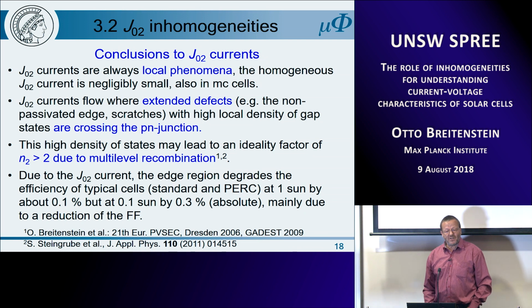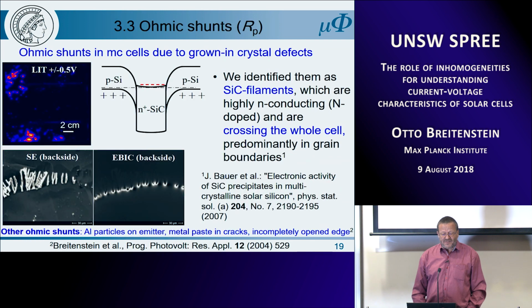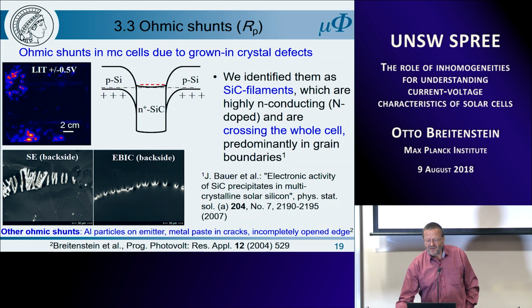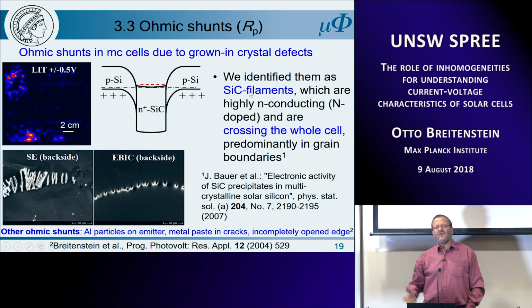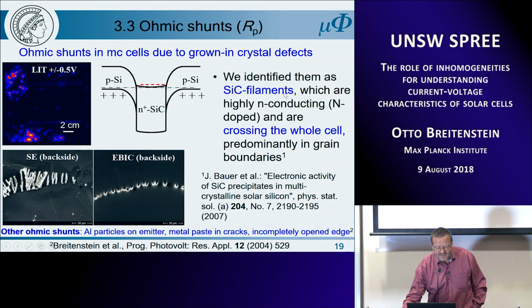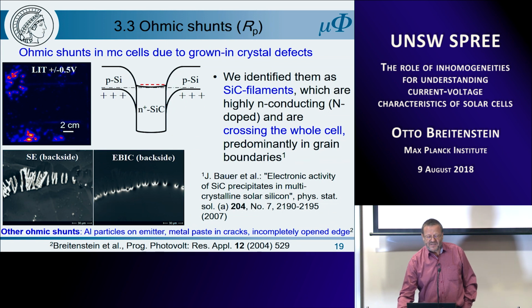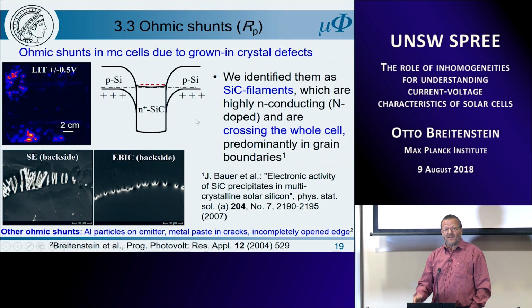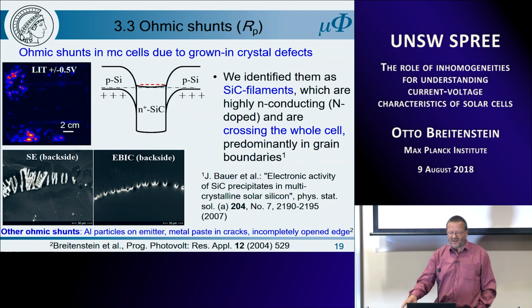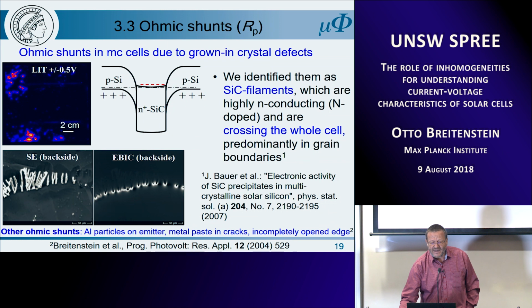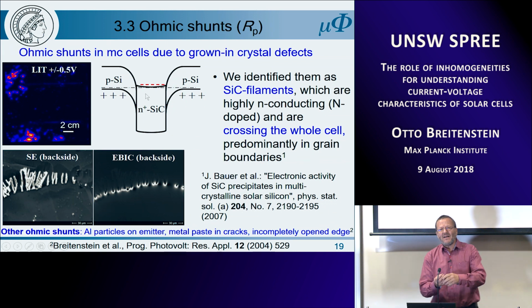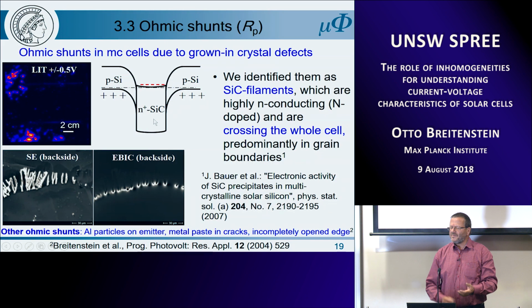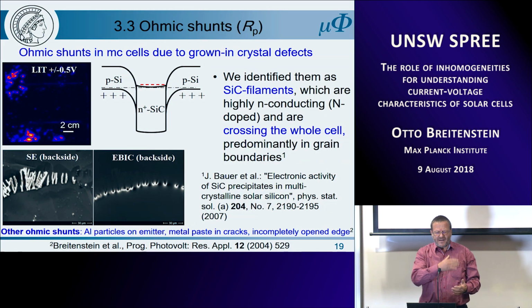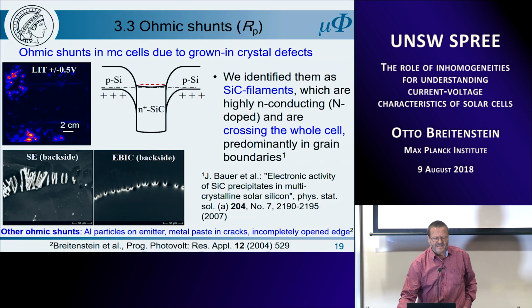Now let me come to ohmic shunts. In multicrystalline material, the most prominent ohmic shunts are due to silicon carbide filaments crossing the whole cells. This was also identified by us already in 2004. We have dissolved them and measured them separately and have found that they are n-conducting silicon carbide, and these are filaments which grow preferably in grain boundaries. So they are arranged in lines.